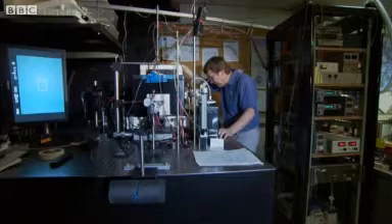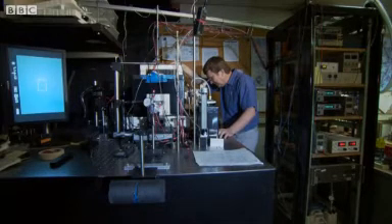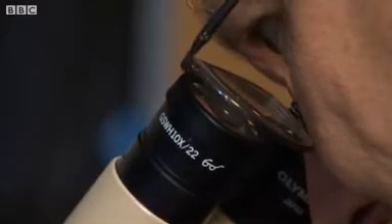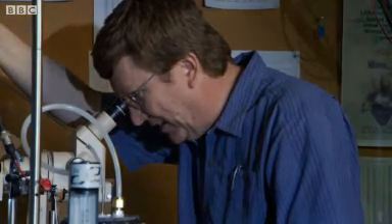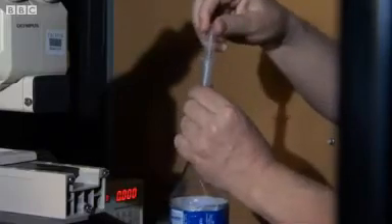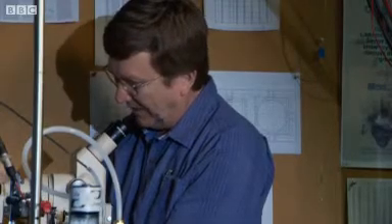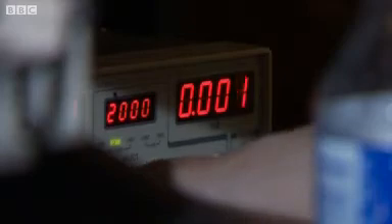So the first thing I'm doing is the needle has a bunch of ice on it, and it's too much. So I've got this little thing in there that is hanging from a thread, and I gently tap that very fine needle to get a lot of the ice off. Then it turns out the growth of needles needs a little bit of chemical stimulant. So this is mostly vinegar vapor, and I put just the tiniest amount of vinegar vapor in the chamber, just a smidgen. Then I turn on the high voltage and I watch and wait, and so now needles are growing, these very, very thin ice needles, and that's big enough.